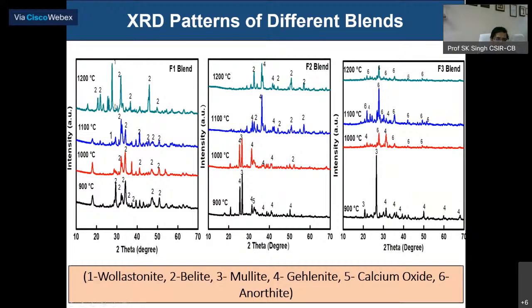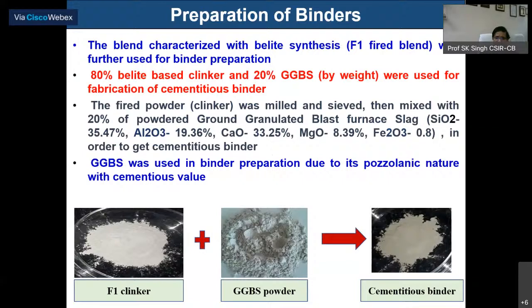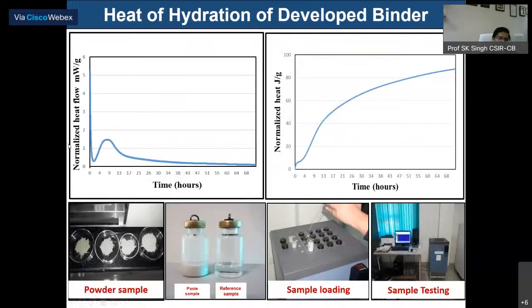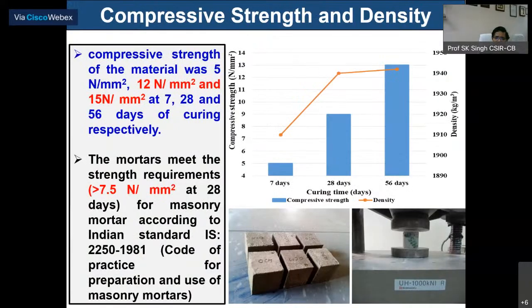If you look at the peaks of alites and belites, all the belites are being converted in the F1 blends, meaning a different type. And we have added some activators, like ground granulated blast furnace slag powder, to make it more and more strong. Here, if you look at the heat of hydration, this second one is a very steep one and is making more calcium silicate hydrate. So for our F1 blend, we have done a calorimetric study, and we are well convinced with this one.